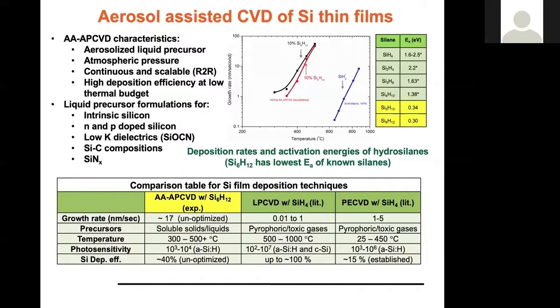Here we're looking at the deposition rate, or the growth rate, as a function of temperature. First and foremost, with monosilane you typically need temperatures of at least 600 degrees Celsius. That requires highly specialized, capital-intensive equipment. Looking at Si6H12 instead, we see deposition as low as 270 degrees Celsius, somewhere in that range.